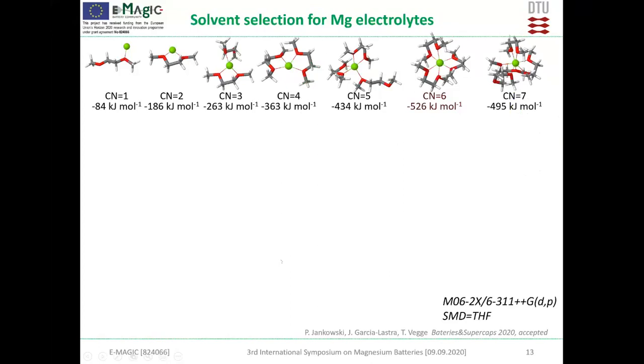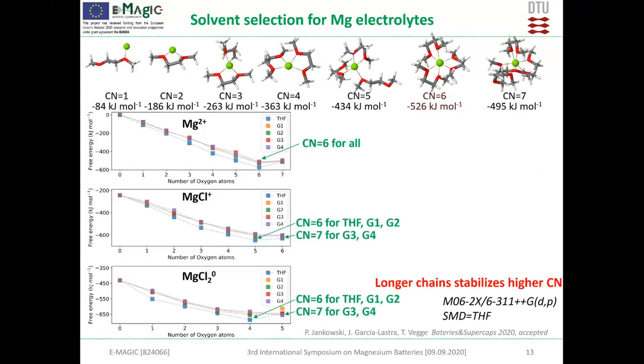To study them, to find out what the structure is, we just need to look at the energies when we add more oxygen atoms close to the magnesium, and then observe where we see the minimum energy, which represents the most thermodynamically stable state. So we can do it for many different solvents and for many different structures with one chlorine and two chlorines. And we can see that for most of them, coordination number 6 is preferred, but for longer glymes, suddenly also 7 is a little more stable.